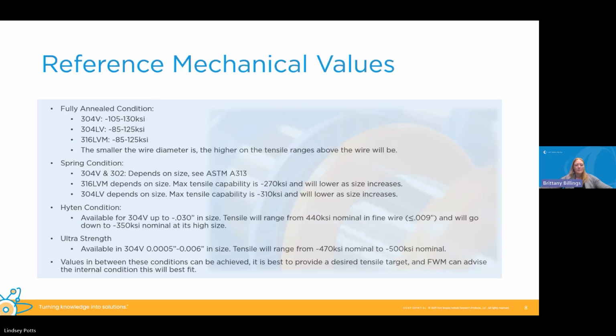And here you can see our reference mechanical values. So starting at the top, you'll see our fully annealed condition. That goes from about 85 KSI to 130, dependent on the alloy. And then the smaller the wire diameter is, the higher the tensile range is going to be.